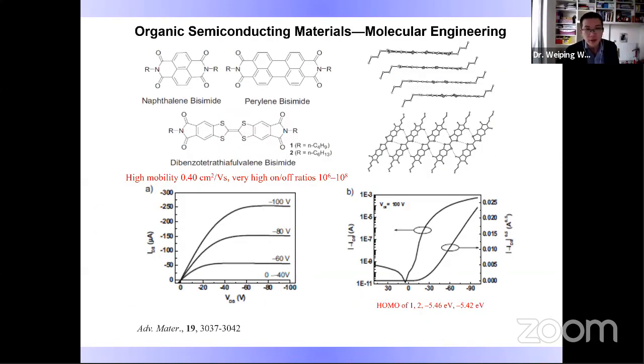Then we further redesigned this type of molecule by attaching pi electron withdrawing functional groups at the two ends, learning from the famous naphthalene bisimide and perylene bisimide molecules, which is a red dye industrialized by BASF company in Germany for decades. By this approach, we have successfully gotten very high mobility and a very high on-off ratio in organic field effect transistors. And this crystalline structure indicates that this material has very strong pi-pi interactions within the molecule.